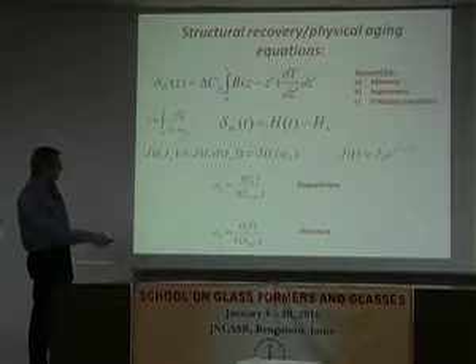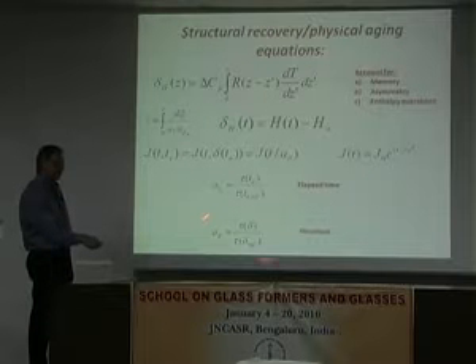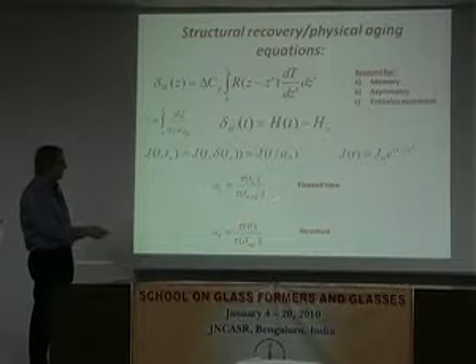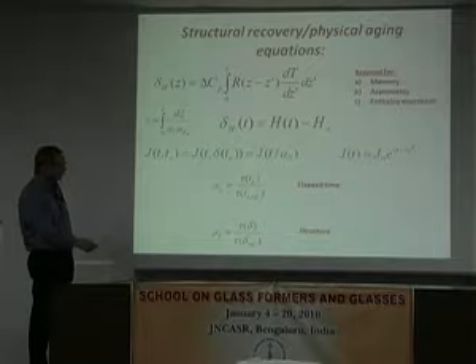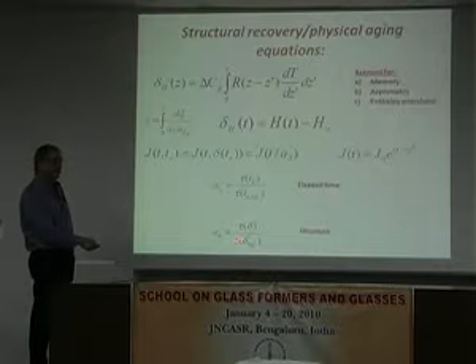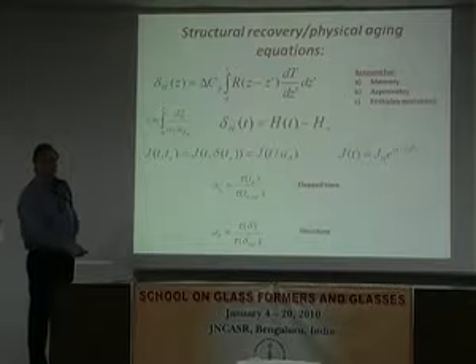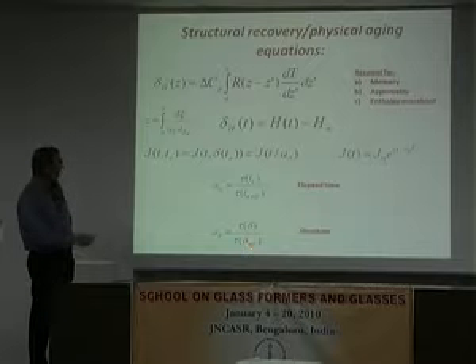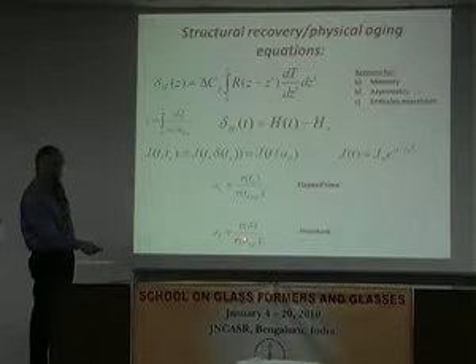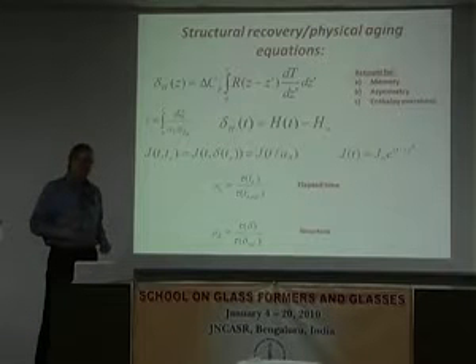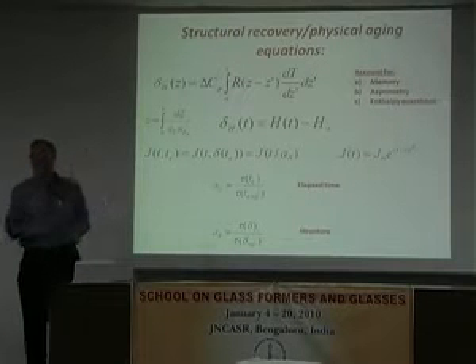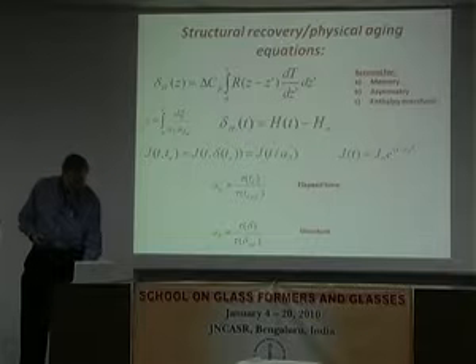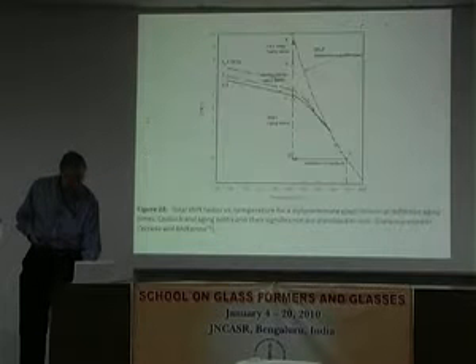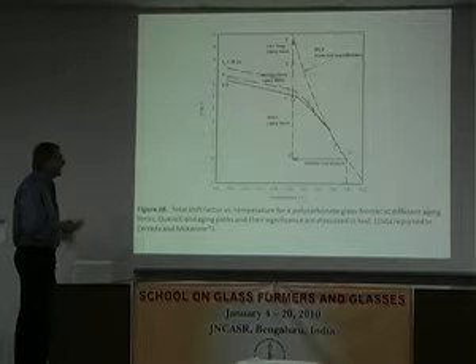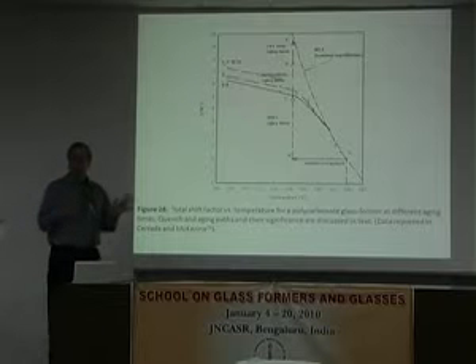But in fact, I should write it this way. It should not be really a function of the reference. It should be a function of some internal parameter in the glass, which has to do with the structure. And I write volume here, or no, actually it's enthalpy in this case, but it could be volume or some other internal ordering parameter, or all considerations of that non-equilibrium thermodynamic state. And when I do that, then I have to imagine some limits, because I didn't feel like doing this calculation.